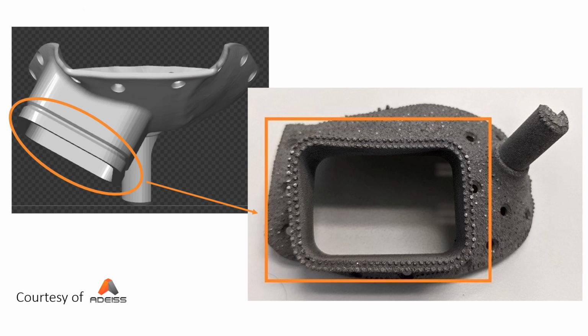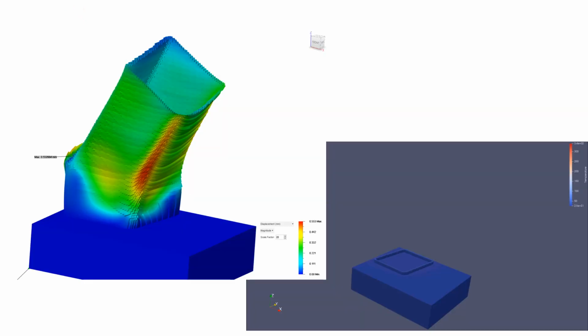So what we've done here is to use simulation with a nominal 50mm, 1mm thick tube that's tipped over at an angle, and this is the result of the simulation. This is using Autodesk Fusion. And we can see our eyes automatically drawn to the area of maximum distortion here. The distortion's been exaggerated by a factor of 20. But really the distortion we're interested in is the opening of the aperture at the bottom here. And it's still somewhat difficult to see what's going on. Number one, is that distortion what we saw? And even if it is, what was really the root cause?